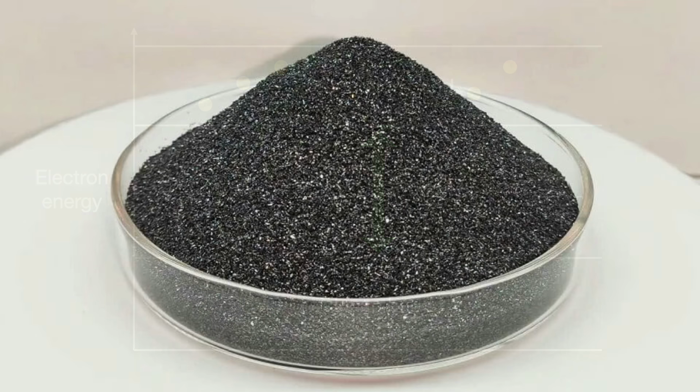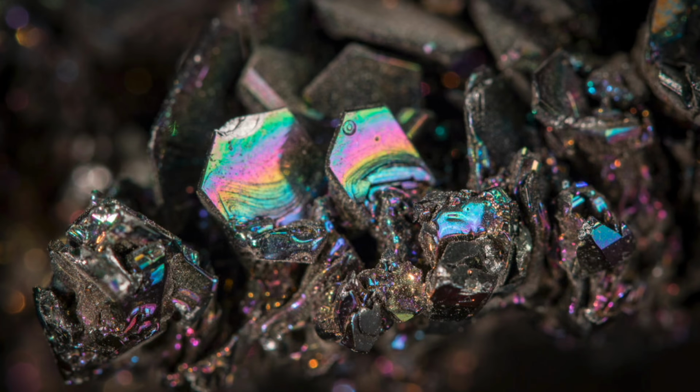Silicon carbide not only has a super wide band gap, but it is also an excellent conductor of heat, 3 times better than traditional silicon, and second really only to diamond. This conductivity makes it easier to extract and dissipate heat from any such device, not a bad perk. Commercial silicon semiconductors thus top out at about 175 degrees Celsius before they break out of their band gaps. Silicon carbide, on the other hand, can go up to 300 degrees Celsius and beyond, maybe even 900 degrees with the right packaging. This wide band gap has applications beyond just heat resistivity.